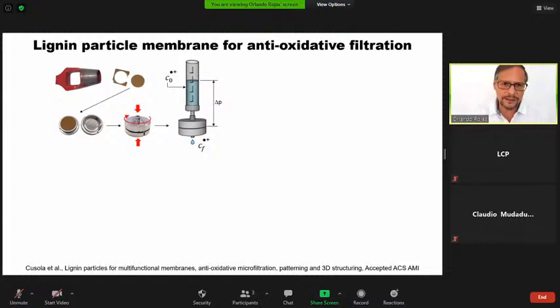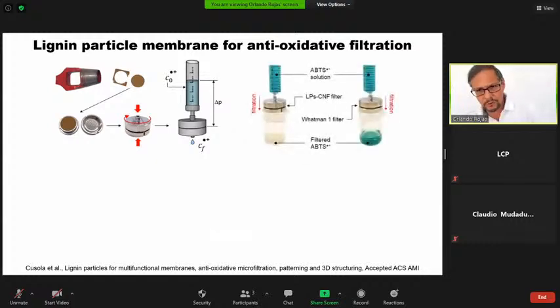And in this case, we put this in a syringe and we use them to produce antioxidative microfiltration. And it works quite nicely. And on the right, we demonstrate the antioxidant capacity of lignin, which is well known: a membrane free of lignin is not able to change the color of an ABTS solution on the right, from the one on the left where the membrane contains lignin particles and very rapidly is able to produce a reducing effect and an antioxidative microfiltration.